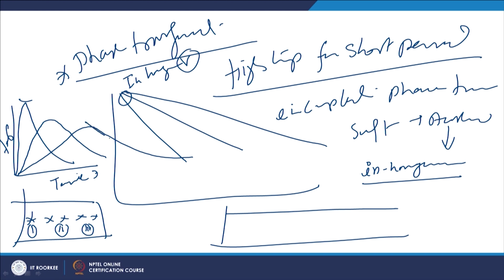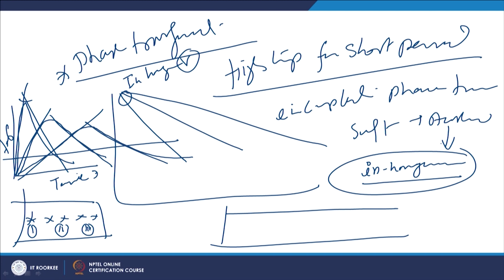So, this slope indicates the cooling rate being experienced, and the slope during the heating indicates the heating rate. Above a particular temperature line, it will indicate for how long a period the temperature above that value is being retained, and that will govern the kind of homogeneity or heterogeneity that will exist in the austenite. And this homogeneity of the austenite is very important for the required phase transformation as per the composition of steel, but if it is not so, then it will lead to a reduced hardening tendency, or reduced tendency of phase transformation into the hard phases.